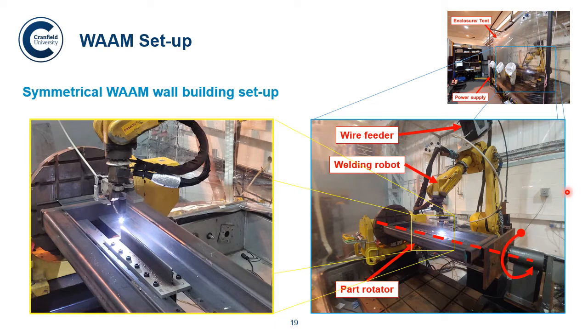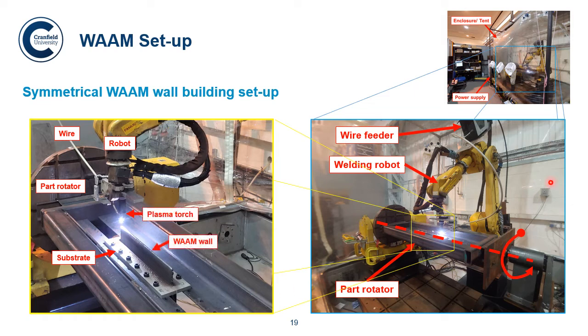And then if we zoom in on the head of the robot, we can see where the wire is coming in, which feeds directly to the torch, the robot, the part rotator, the substrate plate, which is this whole plate which we're going to be welding on top of. We have our plasma torch, which is going to allow us to build our WAAM wall, which is what you can see on top of the substrate. And we have our jig, which everything is attached to. And our inert atmosphere is, of course, argon.